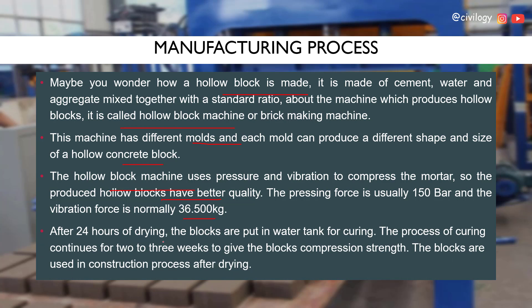The pressing force is usually 150 bar and the vibration force is normally 36.5 kg. After 24 hours of drying, the blocks are put in water for curing. The curing process continues for two to three weeks to give the blocks compressive strength. The blocks are then used in the construction process after drying.